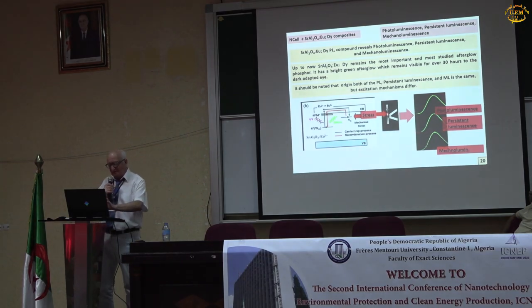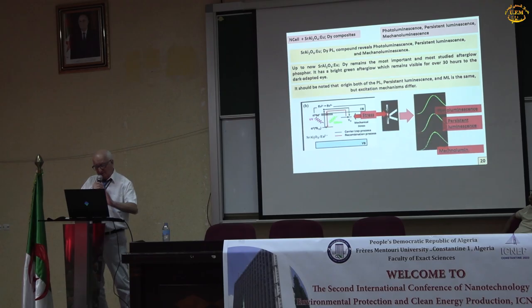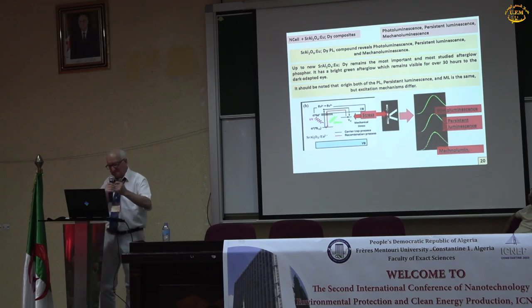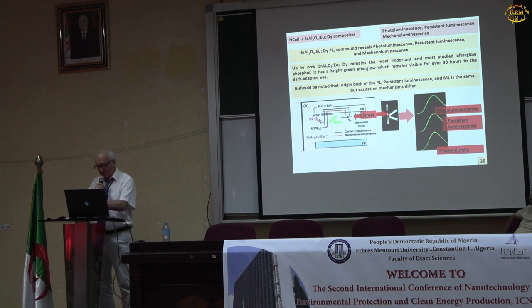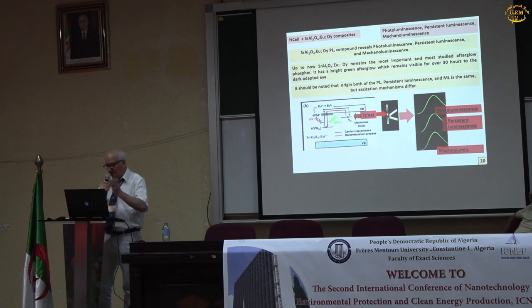Here you see the scheme that explains these luminescence properties. The main part of the scheme is the level of electron traps. Before the experiment we have to excite, to populate these levels with electrons, and after that we apply mechanical stress, for example. Electrons go to the conduction band, and then we see the luminescence of europium 2+ ions. The photoluminescence spectra, the so-called persistent, very long-lived luminescence, and the mechanoluminescence are the same, which confirms the same nature of this type of luminescence.